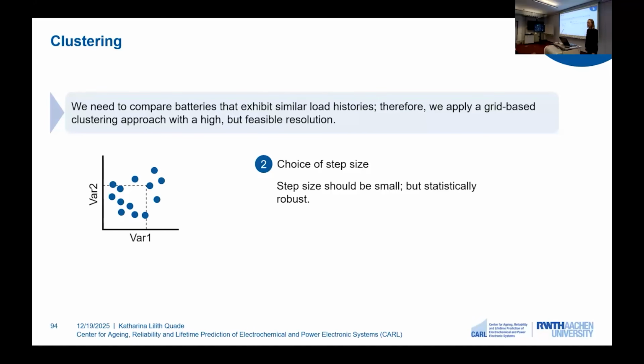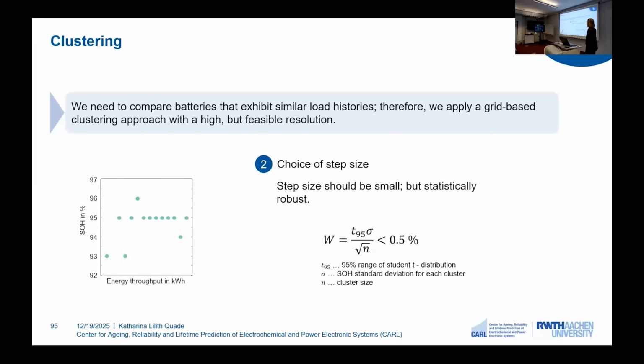The second step is the choice of the step size, so the granularity of our clustering approach. And here we apply a so-called robustness condition, where we say a cluster is robust if the 95% confidence interval of its mean is inside a plus minus 0.5% band. And let me explain visually how this works. Here on the left-hand side, we can see some data points over energy throughput. And let's assume we have a step size that only includes 5 data points. So our n is low and our sigma is high. And now we can calculate the mean plus minus 0.5%, calculate the 95% confidence interval, and we can see that the W is higher than our allowed uncertainty.